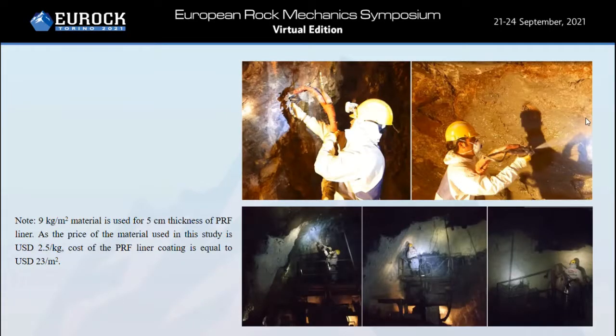In the field study, spray application of the PRF liner was found to be practical and have no rebound problem. Because of the rapid polymerization, PRF liner started to foam as it was sprayed on the wall. As a result of its frothing, a much lower amount of material used in comparison with the shotcrete amounts was seen to be enough in PRF applications.